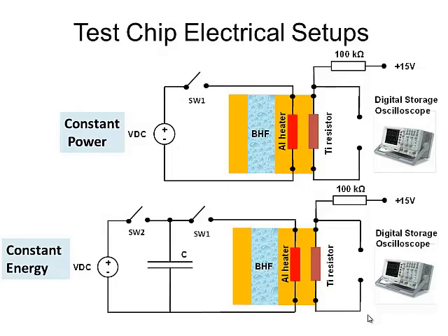To detect the chemical attack on the chip, the resistance of the titanium test resistor was monitored by connecting it to a series 100 kilo ohm resistor and a 15 volt DC power supply. The nominal test resistance of the resistor was 60 kilo ohm. The voltage across the test resistor was monitored using a digital storage oscilloscope.